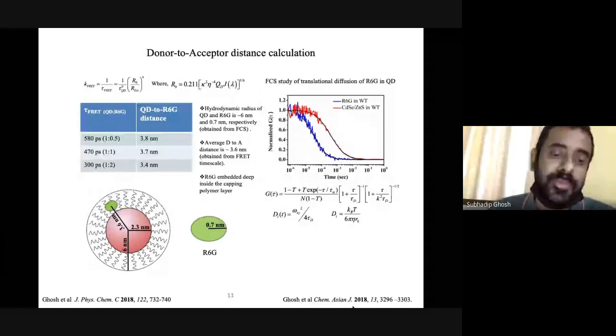So the next step is finding the donor-acceptor distance, because we know FRET is used as a molecular ruler. So obviously, it is of common interest to measure the donor-to-acceptor distance from the FRET time scale. Using this equation, the FRET rate we can get from the quenching rate, and tau is the time scale, and R0 is the Förster distance calculated theoretically using this equation, and RDA is the donor-to-acceptor distance, which is our interest here, and tau 0 is basically the lifetime of the donor in the absence of acceptor.